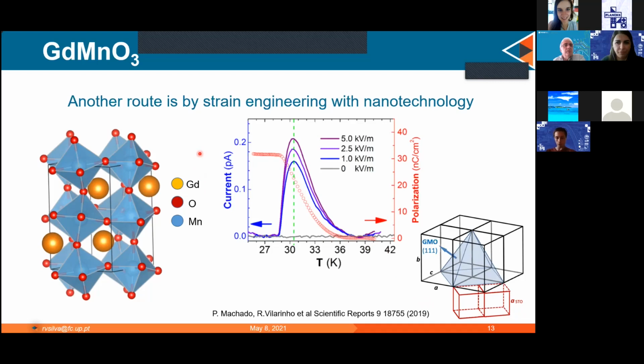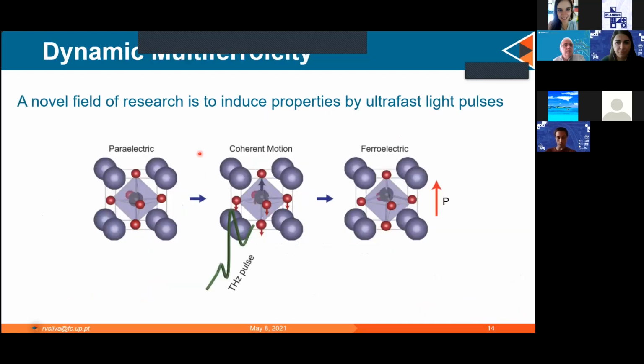Then there is a new research field that is appearing in some research groups, and we are also joining this, which is instead of having a multiferroic material, we have a dynamic multiferroicity. And what this means is that we join forces with another group within IFIMUP of ultrafast lasers. And what you do is you take any kind of material, some paraelectric, paramagnetic material, then you apply a terahertz pulse, terahertz because it's a wavelength that is good to make motions of the atoms, and you have a coherent motion of the atoms. You move this atom up, this downwards, and you have a local electric polarization. So the material now is ferroelectric.